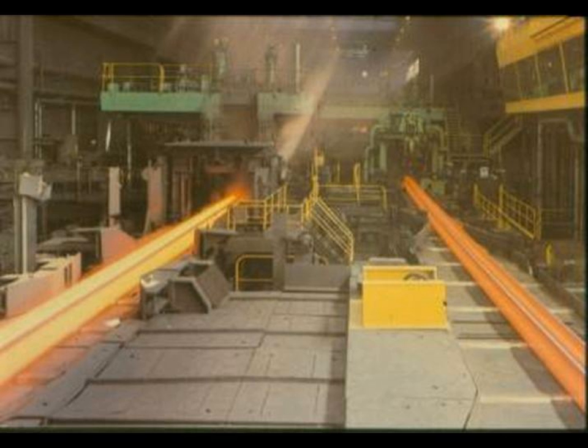If we go to the mill and watch these shapes being produced, we can see that the whole cross-section doesn't cool uniformly. Now, for the member on the left, and these are being rolled and coming out in the H configuration, if you will, you can see where the tip of the flange has cooled more, and you see a darker color associated with the tips of the flange.